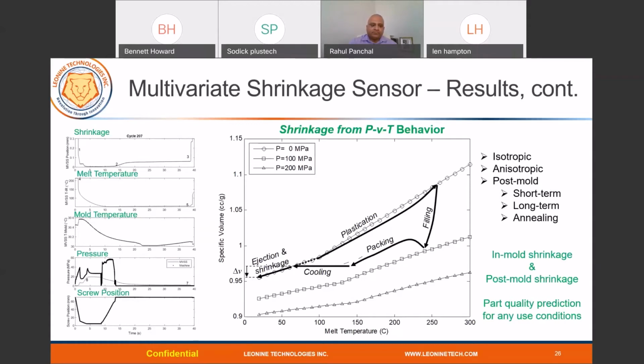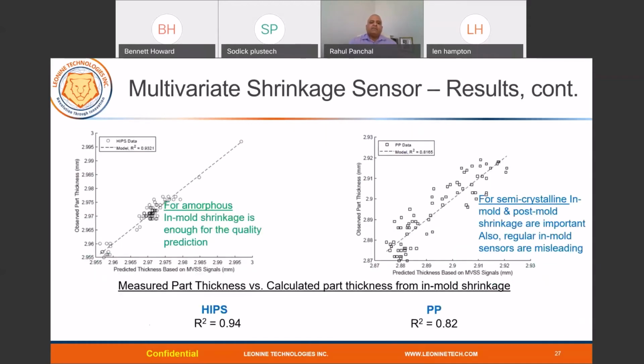Again, we measured the part thickness at the sensor location and calculated the part thickness from the sensor data. For HIPS, we got 94% correlation, and for polypropylene, it's 82%. It improved a little bit, but it didn't improve enough, so we're still working on that. We know where we need to work to improve the polypropylene correlation. But still, again, it's way better than any other technology available.